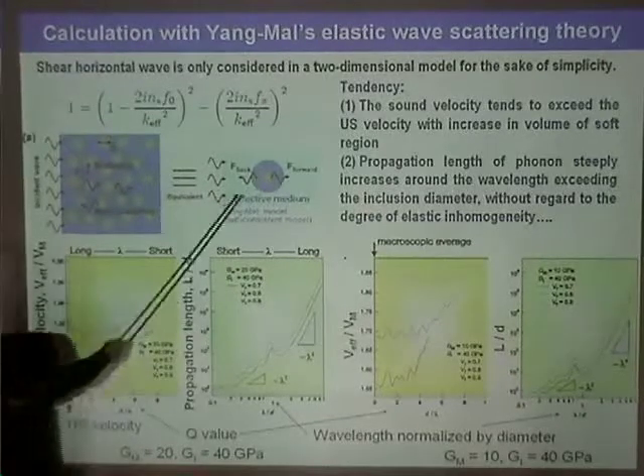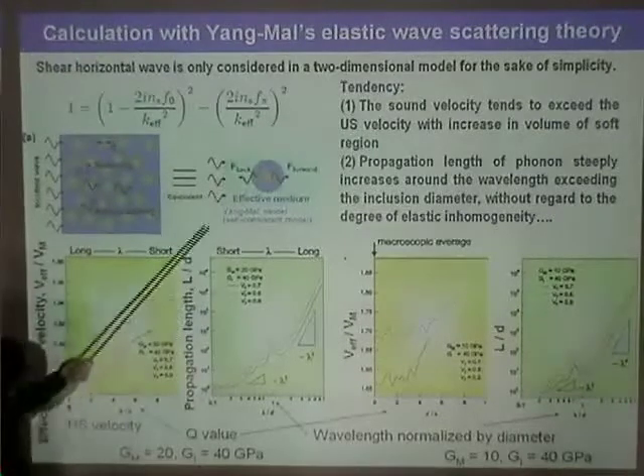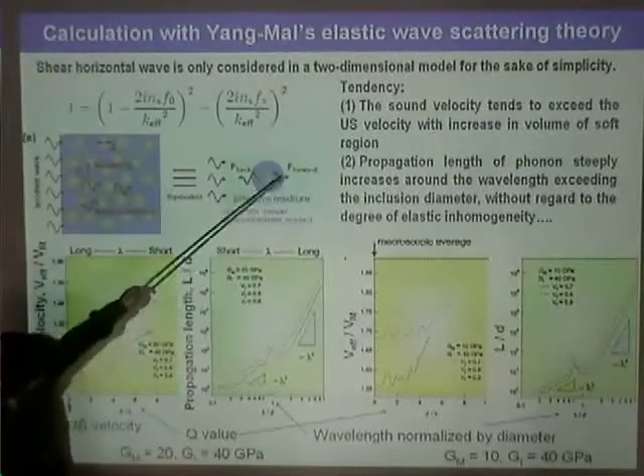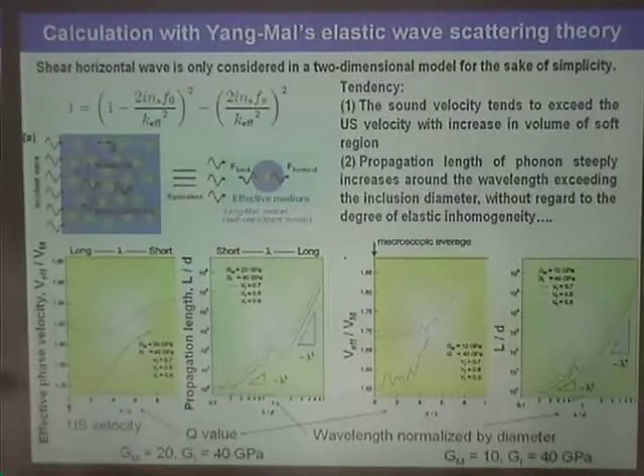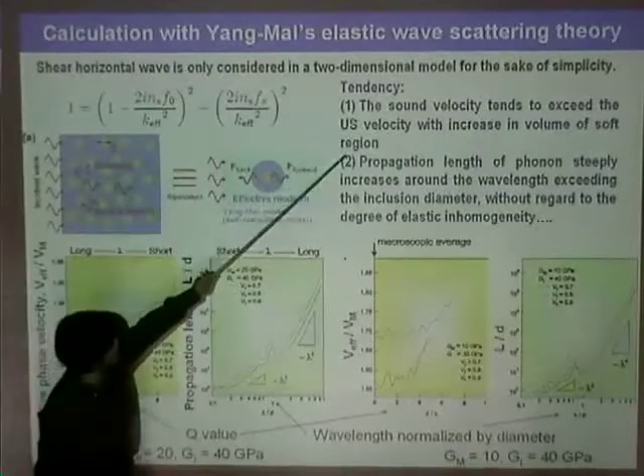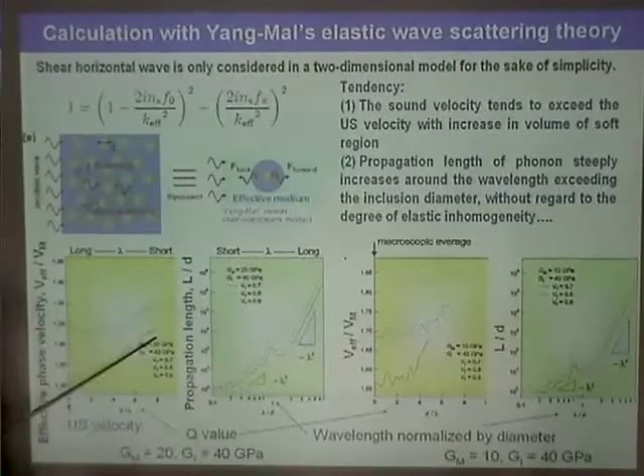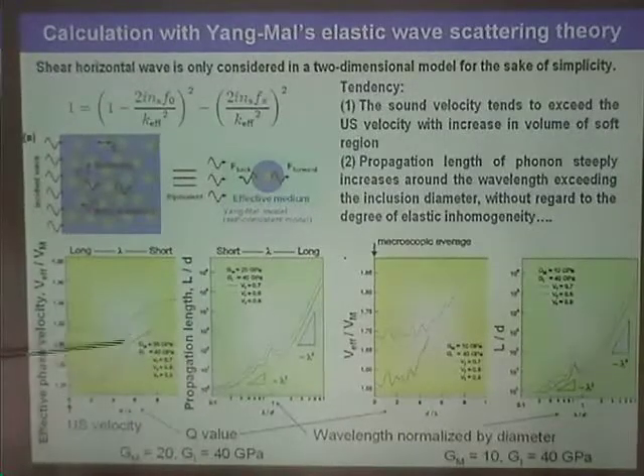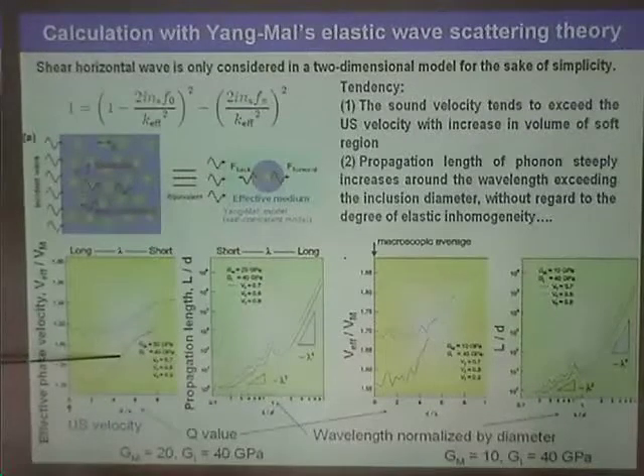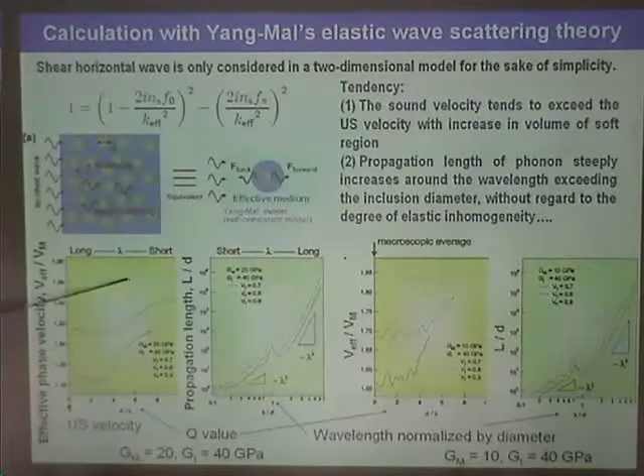So we can see the tendency in the calculation. The sound velocity tends to exceed the ultrasonic velocity with increase in the volume of the soft regions. The red case is where the fraction of the soft region is 0.7, and this is where the soft region's volume fraction is 0.1.